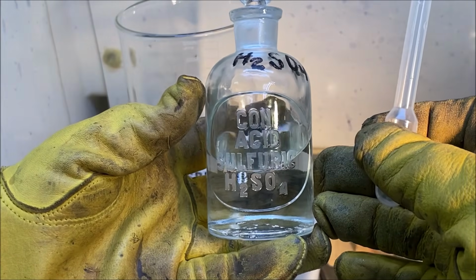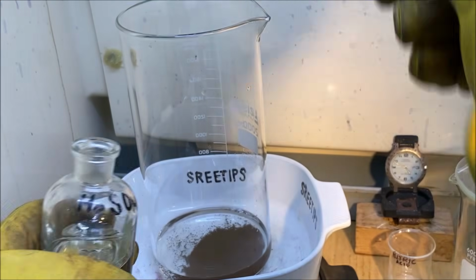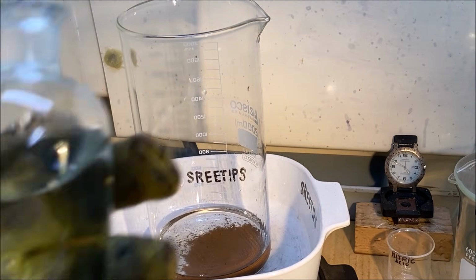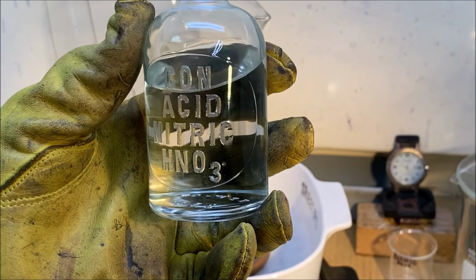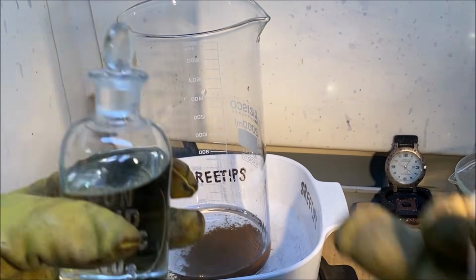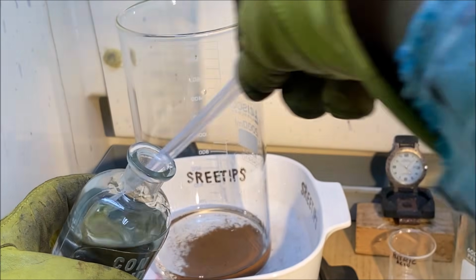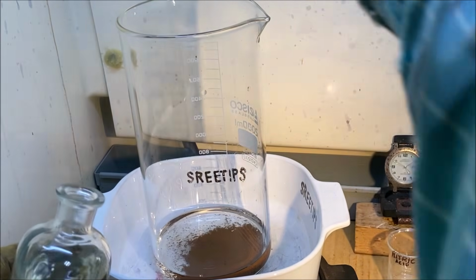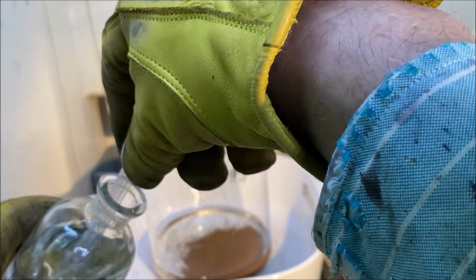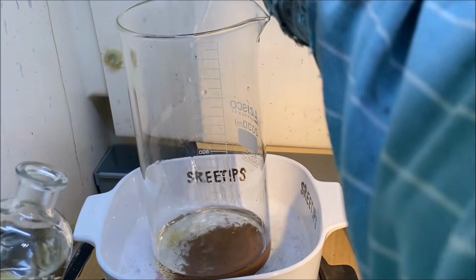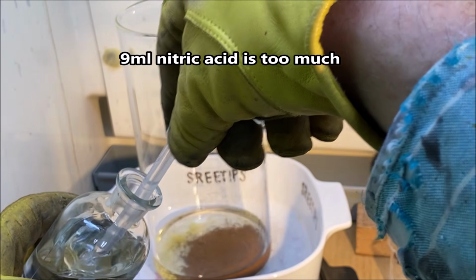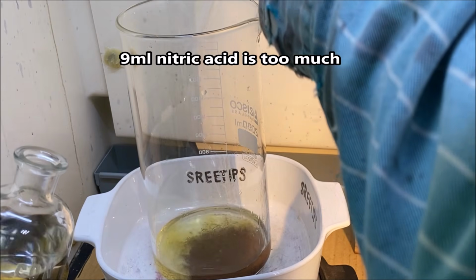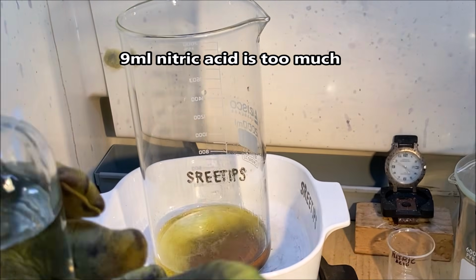Add a little dribble of sulfuric acid, to get any lead out that might be in there. A couple shots of nitric acid. Should only take about 6 milliliters of nitric to get this to go in the solution completely. Now let's make it 3 milliliter doses, 9 milliliters of nitric acid.